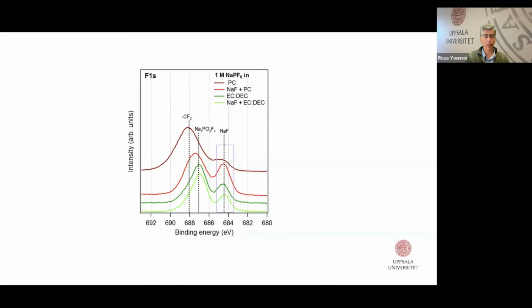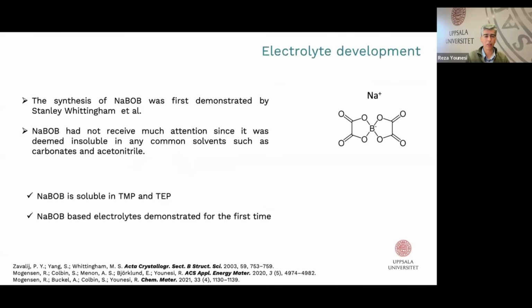Another related topic I want to highlight when it comes to SEI and sodium-ion batteries is related to this salt, sodium BOB - probably you are very familiar with lithium BOB, which has been used for lithium-ion batteries. The interesting thing with sodium BOB is that it's very difficult to dissolve in most common solvents. Sodium BOB was actually first demonstrated by Stanley Whittingham some years back, but it wasn't used in any battery application because it's not soluble in carbonate and ether-based electrolytes.